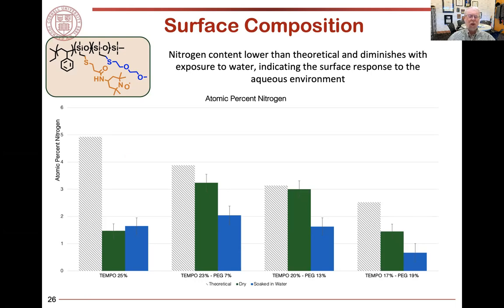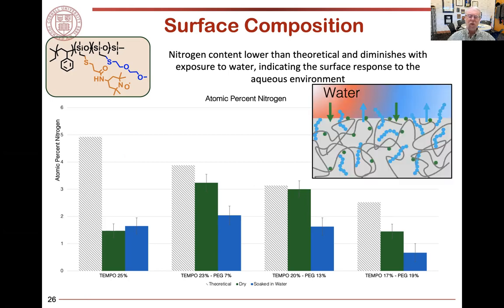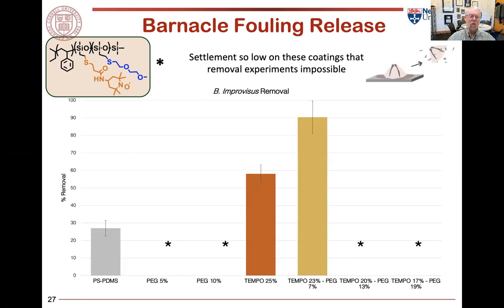TEMPO, but because they're in close proximity to each other, wherever the PEG is going, it's dragging along some of the TEMPO. And arguably, it's close enough to the surface region that it's still going to have an effect on any type of chemistry that's occurring in that region. So PEG draws it to the surface, and it stays there, and we believe it's accessible. So in fact, if we look at barnacle fouling and release, we find that PEG is helpful.